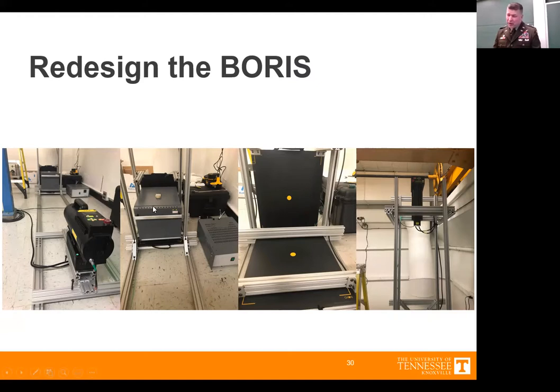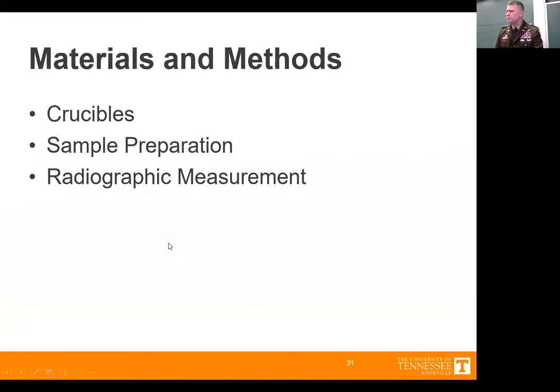I also had to change the furnace because of the location of the heating elements in the other furnace. The other furnace was much more efficient at heating and controlling the temperature. However, that did not make for very good radiographs. So this configuration yielded the most usable radiographs and was able to provide the most information, the most bang for the buck. So this is the system that I built.